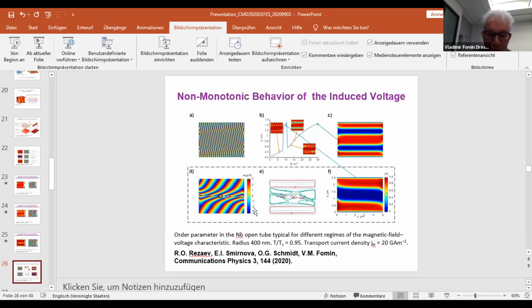But the vortices and anti-vortices are now occurring with very high speed. So the typical time of life is 10 to the power minus 15 seconds, while for vortices it's 10 to the power minus 11. So these vortices and anti-vortices move very fast. Because of that, if we calculate the voltage induced by the moving vortices and anti-vortices, as shown here, in this window of magnetic fields where this phase slip occurs, we see a clear peak.